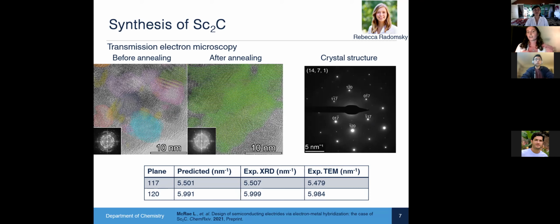And there's a huge potential for energy storage, but there's not a huge change in lattice spacing. There's only really a 5% decrease in the lattice size. And so it's very useful for a battery anode, because fluoride ion batteries do not yet have intercalation anodes, and conversion anodes tend to degrade really quickly. And so this material could be really useful to fill those needs as a battery anode.